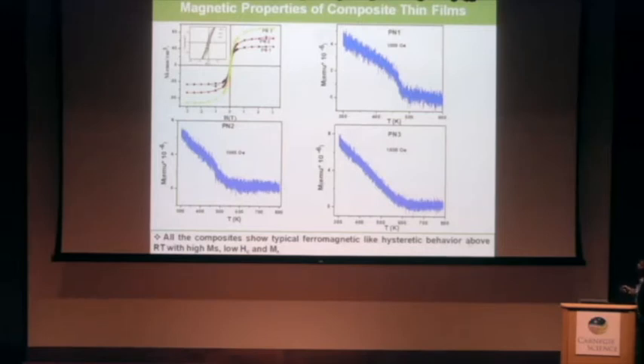So these are the magnetic properties of the composite thin films. Here you can see the PN1, PN2, and PN3 thin films. They have very low coercivity and low remnant magnetization. Here also we observed that as we increase the magnetic content, and these are the field-cooled curves taken at 1000 Oersted, the magnetic transition goes on increasing.